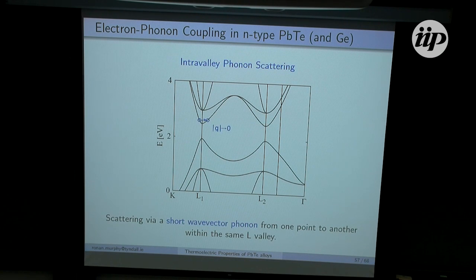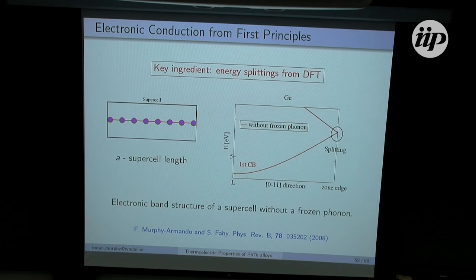The second type of interaction we take into account is intravalley scattering. This is where you can imagine a very short wave vector phonon scattering an electron from one point in the L valley to another point within that same L valley. Now, I'll very briefly give you a sense of what it takes to calculate this quantity in the case of intravalley acoustic scattering. To do this, you need to find a splitting in the conduction band energy due to the presence of a phonon. So you construct a supercell, like this little mock-up here. You calculate the electronic band structure, and then you measure from L along a specific direction out to the zone edge, and you get this here.